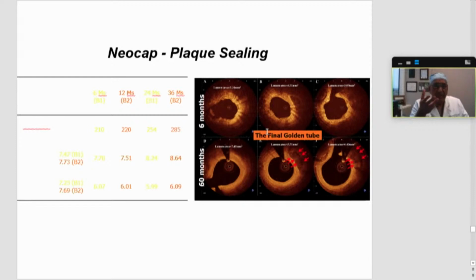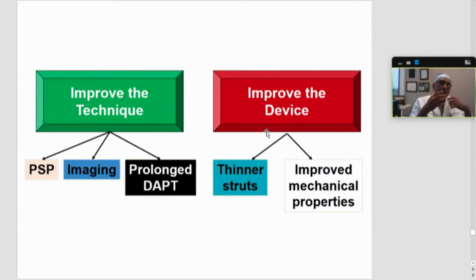Not only that, the neocap, the plaque seals usually at about 2 or 3 years. But then the stent thrombosis remains a big concern. So we try to work around that, not only avoiding it in small vessels, but improving the technique. So, for example, post dilating the BVS Absorb, making sure every case has imaging, and then prolonged DAPT, whether 12 months or maybe even 24 months. But the real challenge is going to be in continuing to improve this device if we believe BVS is the future of human coronary stents, whether we make them thinner struts, or we improve their mechanical properties.